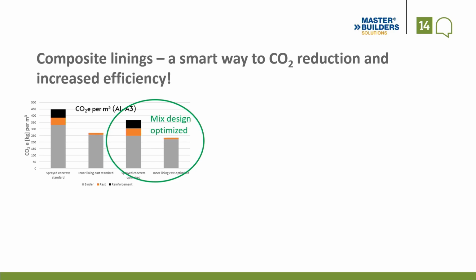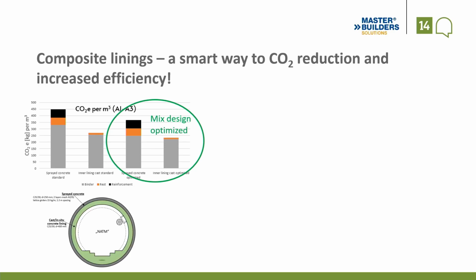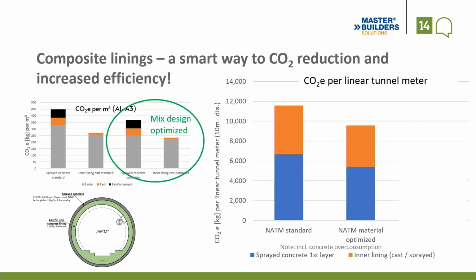And I want to know how many kilos or tons of CO2 I need per linear meter of tunnel, then I need the geometry. And to make my mathematics easier, I used a round shape. I know this is not the right shape for an NATM tunnel, maybe for a TBM, but forgive me for that. It is 250 millimeter sprayed concrete with 2 layers of mesh, 1.3 meter advance lengths with lattice girders, and the 400 millimeter cast inner lining, and the sheet membrane and geotextile in between. Then we do the mathematics for our 10 meter diameter tunnel, and that's the outcome.